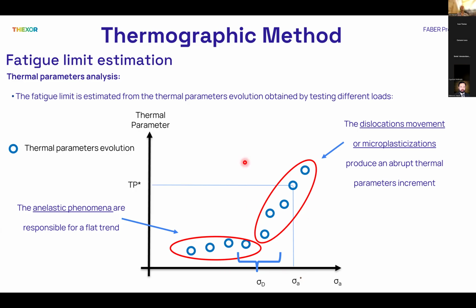From this graph, there are mainly two different trends. There is a flat trend near low stress amplitude as a consequence of the anelastic phenomena involved during the fatigue test. On the other hand, there is another trend corresponding to an abrupt thermal parameters increment, occurring for high stress amplitude, mainly caused by dislocation movement or microplasticization effects. So at the end, the fatigue limit is located between these two trends.